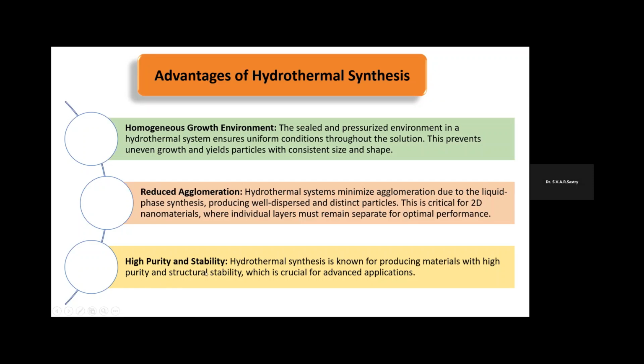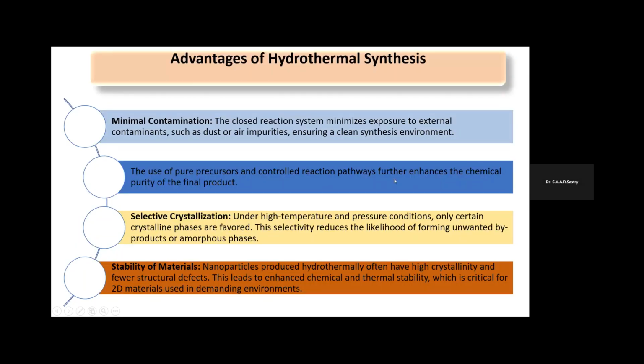In addition, we also have high purity and stability of the finally formed nanoparticles. Hydrothermal synthesis is known for producing materials with high purity and structural stability. Further, we have minimal contamination because the system is closed; the autoclave is sealed. This closed reaction system minimizes exposure to the external environment, external contaminants like dust or air impurities, ensuring a clean synthesis environment. Further, the use of pure precursors as raw materials, reactants, and controlled reaction pathways also enhances the chemical purity, because we don't have any side reactions or undesired reactions here.